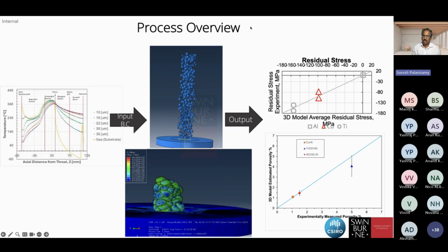But again, from the residual stress point of view, you're not inputting too much heat. You're not using a laser or electron beam. So the residual stress will still be there, but comparatively far lesser than SLM or other processes, I would say. But still the residual stress will be there, because you're still creating powder particles embedded together. So residual stress comes from the bonding mechanism in which it's done. So still the residual stress will be there. You can see.